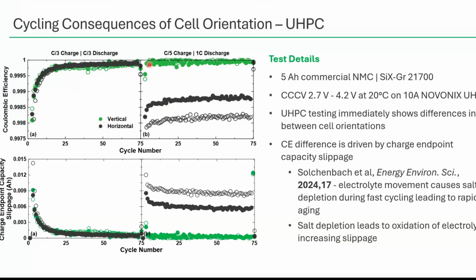The vertically oriented cells allow electrolyte to travel back into the jelly roll a lot more uniformly. Whereas when we turn the cell on its side, electrolyte doesn't just have to get back into the jelly roll - it also has to get around all of the lines and back into the top of the jelly roll in that orientation. So what you end up with is very big, very dramatic salt depletion and concentration gradients depending on how you orient your cell, and this can preferentially lead to oxidation of electrolyte energetically, increasing charge endpoint capacity slippage.